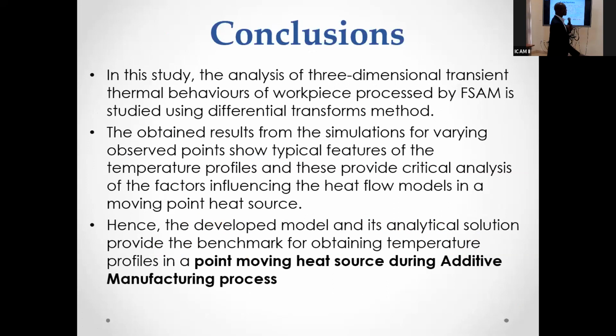In conclusion, in this study, the three-dimensional transient thermal behavior of bodies processed by friction stir additive manufacturing is studied using differential transforms method. The results obtained from the simulations for various observed points show typical features of the temperature profile, and this provides a critical analysis of the factors influencing heat flow models in a moving heat source. Hence, the developed model and its analytical solution provide the benchmark for obtaining the temperature profile in a point moving heat source during the additive manufacturing process.